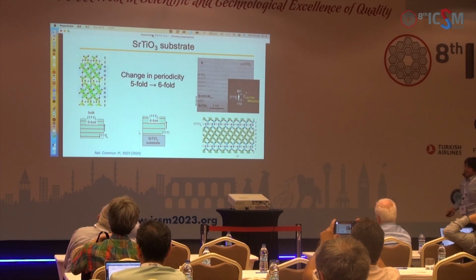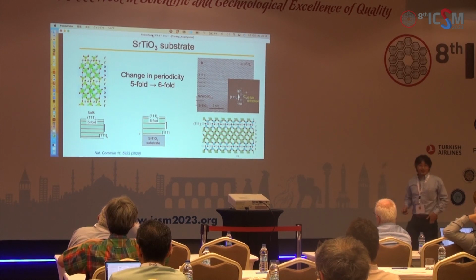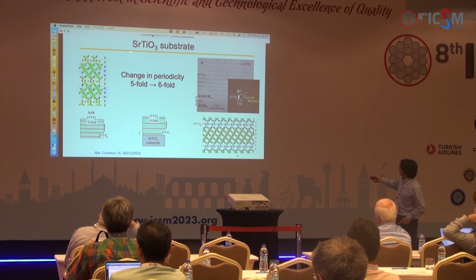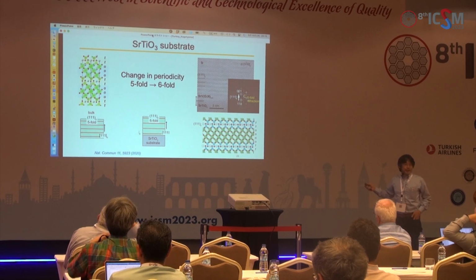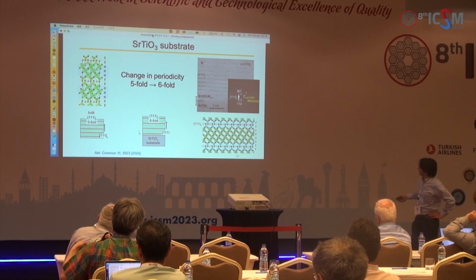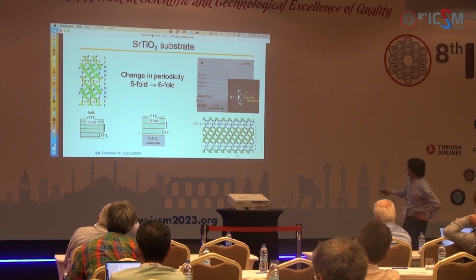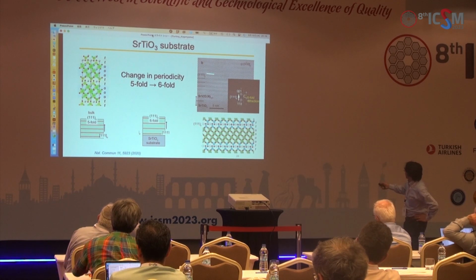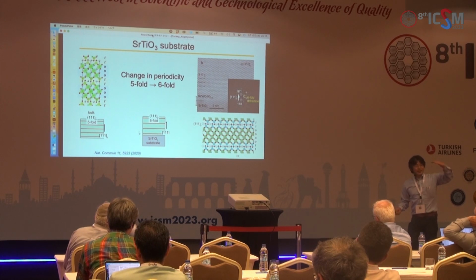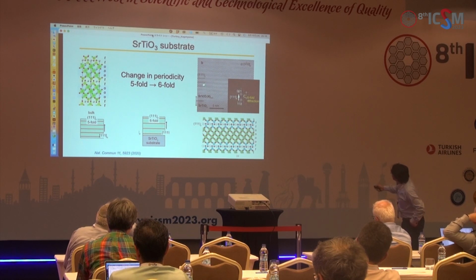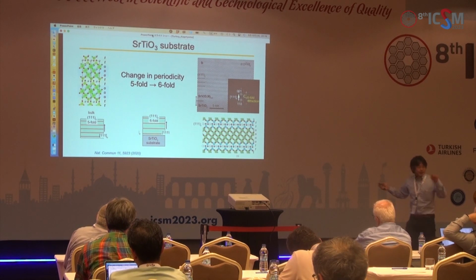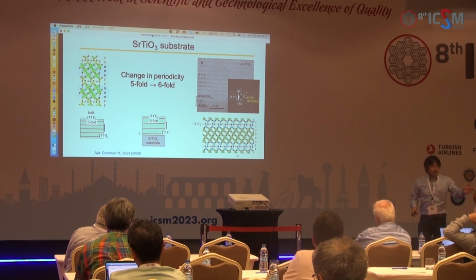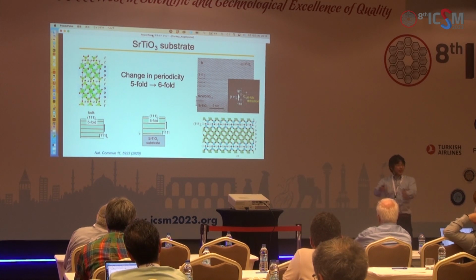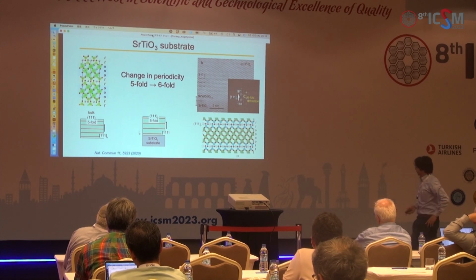Then we continued our synthesis, but in this case we used the strontium titanium oxide substrate, which gives tensile strain. In this case, you see that this is parallel. The oxygen vacancy is parallel, in the 111 direction. But the periodicity, which you can see from these superreflections, is not 5-fold, but 6-fold. Again, by using the strain, you are able to control the direction and the periodicity of the oxygen vacancy.